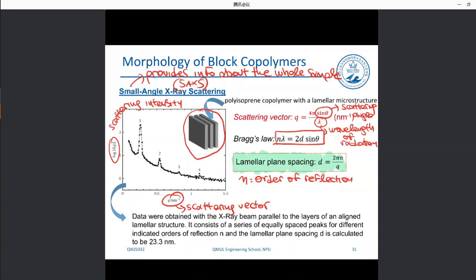As we go to the graph, we can see that the first peak is from the first lamellar plane. So we have one order of reflection, second, third, and the fourth. These represent reflections by subsequent lamellas. And in this way, we can obtain parameters such as dimensions of our structures.